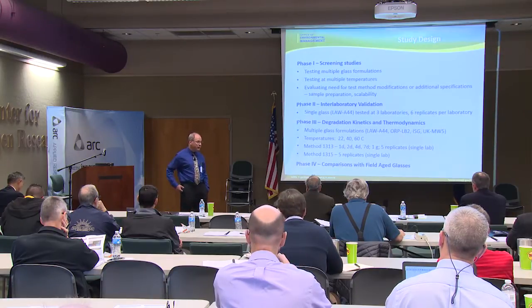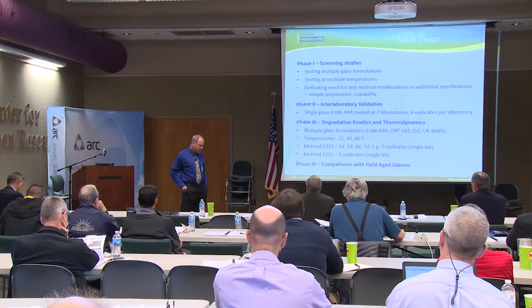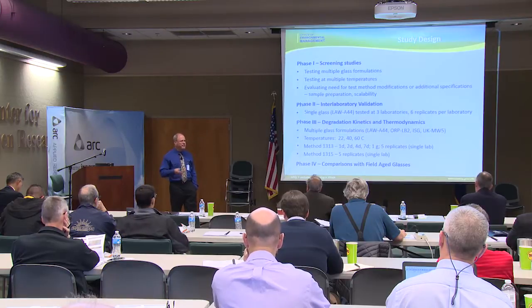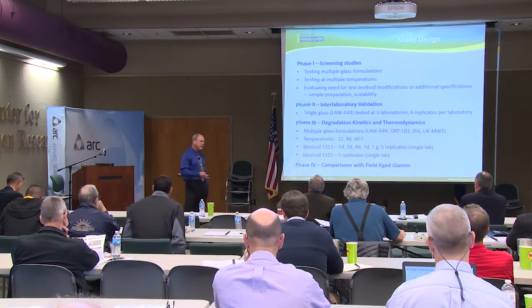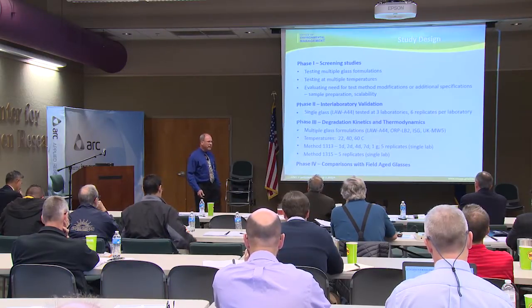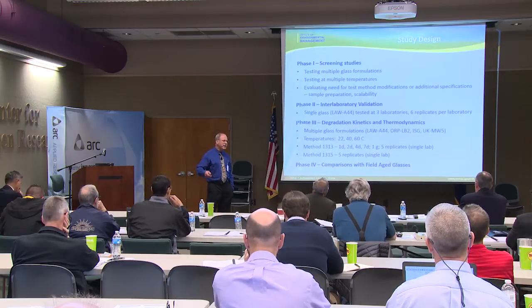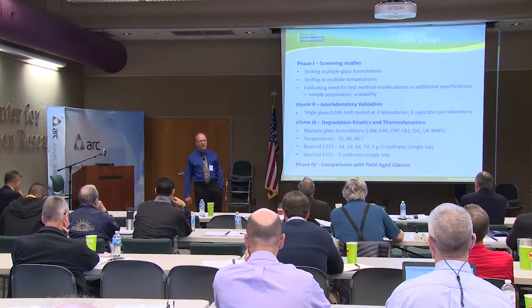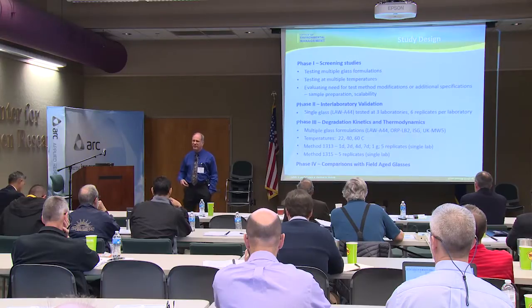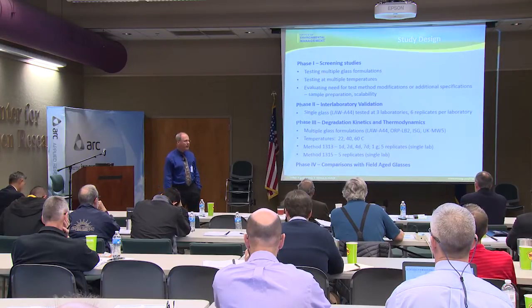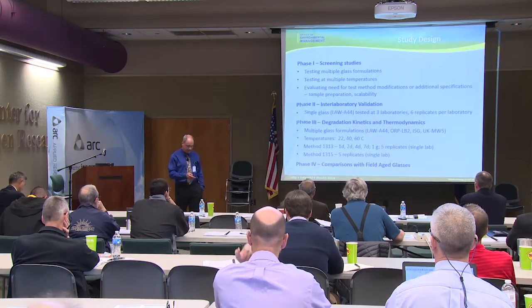And then to take and in the laboratory formulate glass that is of similar composition as what was obtained from the field, and see whether there is reasonable similarity between what would be predicted based on laboratory testing of that laboratory manufactured glass compared to the extent of degradation, the nature of the degradation that's observed from these samples that have been out in the field for very long periods of time.